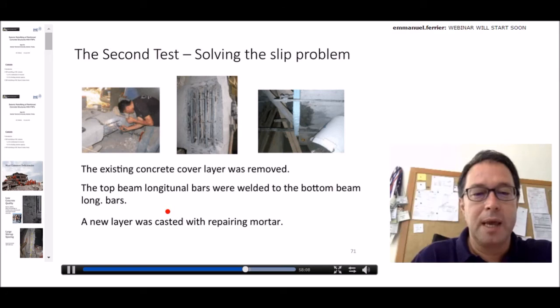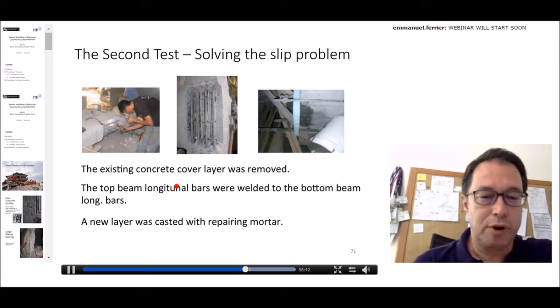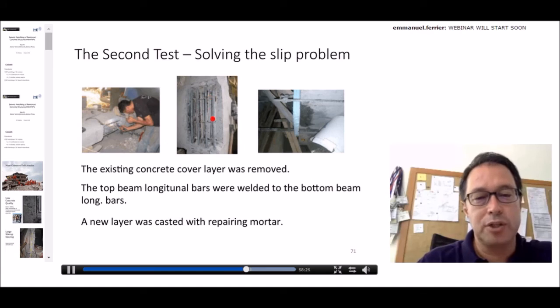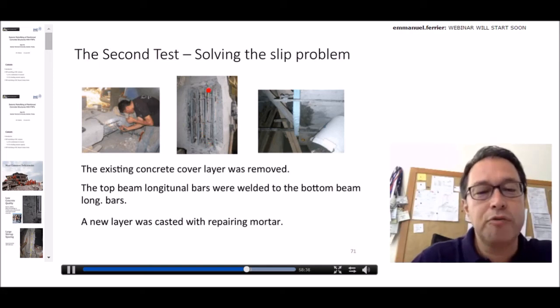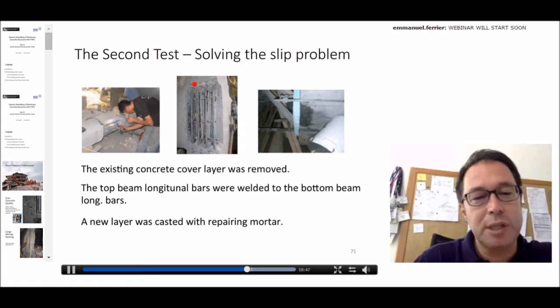And then for solving the problem, of course, first we want to solve the problem about slip, not about the joint. So we wondered what would happen if we solve the problem about slip, but not the problem about the joint. So what we did was, just behind the joint, we broke the concrete on and under the hooks of longitudinal bars. We first welded the hooks of bottom bars to the hooks of top bars, which were all bent 90 degrees up and down. As a second intervention, we replaced the weak concrete here with a higher strength repair mortar. And nothing else. This was how we repaired this one.